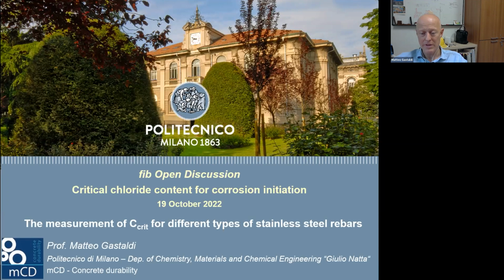Surely the addition of chloride in the mix changes the condition. This is clear. This is the reason why it's fundamental to also evaluate some coefficient that you have to use in order to move from the chloride ratio that you can find with the accelerated test to the chloride ratio that you can find in a non-accelerated test. So you have to consider this. It's fundamental to have an idea also with tests that need a long time or real exposure tests, so in a real structure, in order to have the coefficient that can help you to move from the accelerated test to the real chloride ratio.